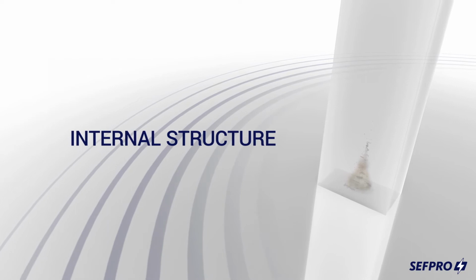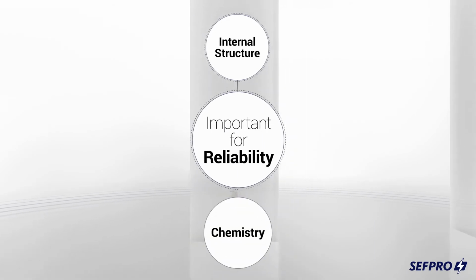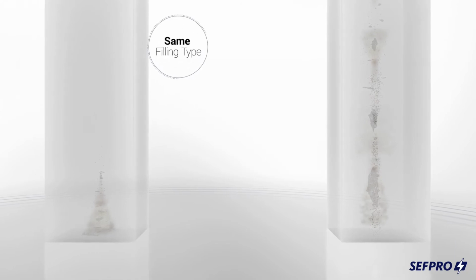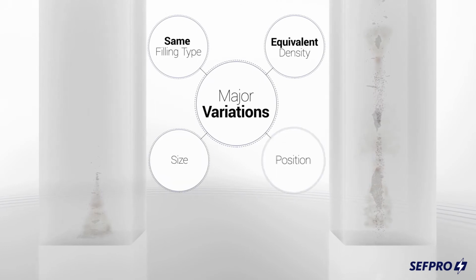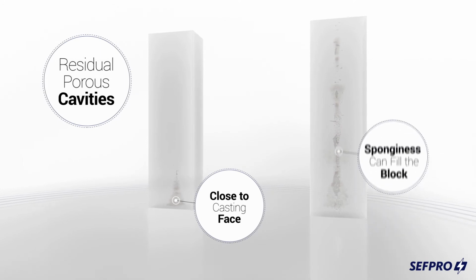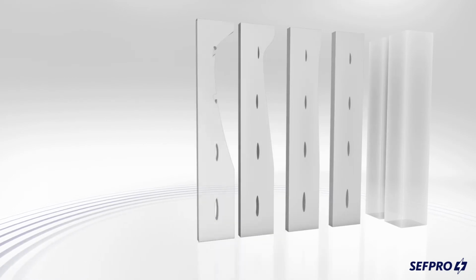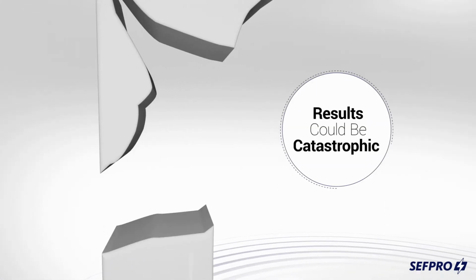Now, beyond DNA, what about the structure of an AZS block? Did you know that the internal structure is just as important as its chemistry for the reliability of your furnace? For two identical blocks of the same filling type with equivalent density, there can be major variations in the size and position of shrinkage cavities. Residual porous cavities can be all located in one place, close to the casting face, or the sponginess can fill the block. Can you imagine what happens if the sponginess is in the most exposed part of the block, the part in contact with the molten glass? You know the results could be catastrophic.